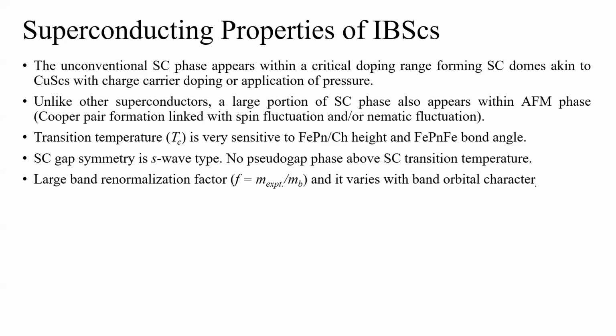The renormalization factor is basically this: if you do DFT-based calculations and compare with the experimentally measured electronic structure, and the renormalization factor is 1, it means that there is no correlation in the compound, and the calculated electronic structure will match the experimentally measured electronic structure.